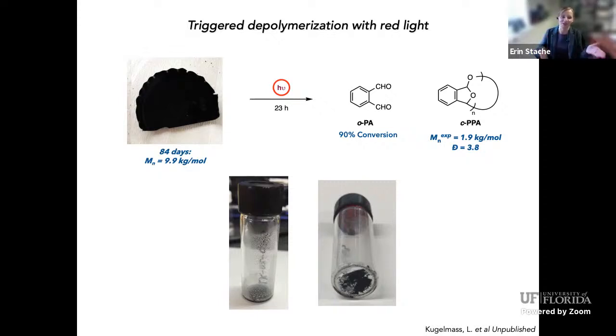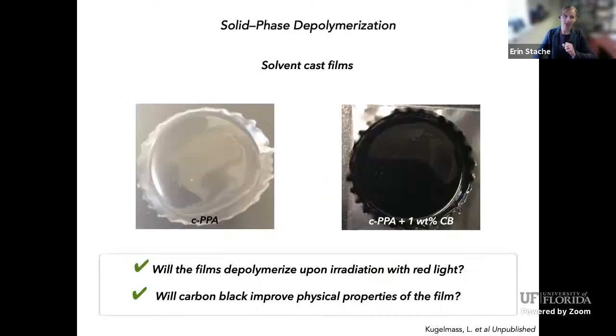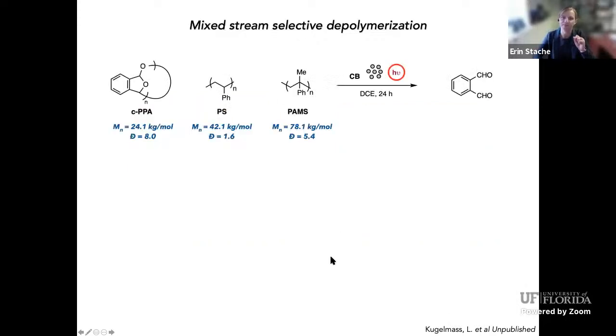So it's a really cool experiment to show that the carbon black is stabilizing and giving this polymer a much longer lifetime, suggesting that this is a material we could embed into our polymers, use the product, and then just trigger depolymerization when we want to by shining more intense light on it, because sunlight itself is not enough to induce enough photothermal heating to get it to depolymerize. So we can depolymerize solid phase films, and the carbon black actually improves the physical properties of the film, which is really exciting. This is something we're going to look at as we explore other photothermal materials as well.